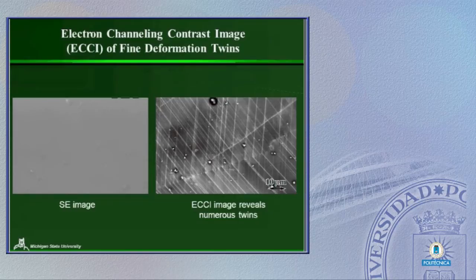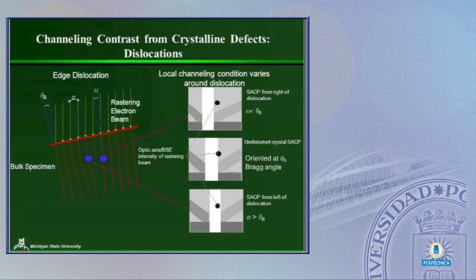This is a secondary electron image of deformed TiAl, and this shows a twin boundary, an annealing twin boundary, and then these fine lines are actually deformation twins. And those are very, very small. You can see in some cases those are on the order of tens to maybe hundreds of nanometers across, so they're very fine twins that we can resolve very easily in the SEM if we set up our imaging conditions correctly.